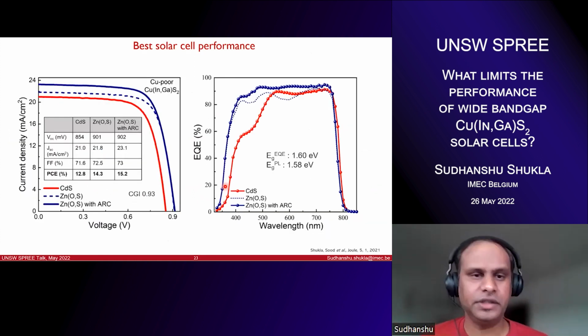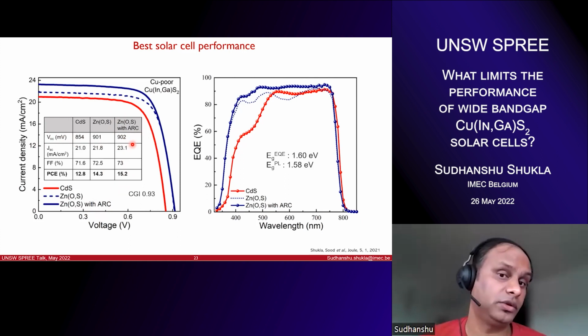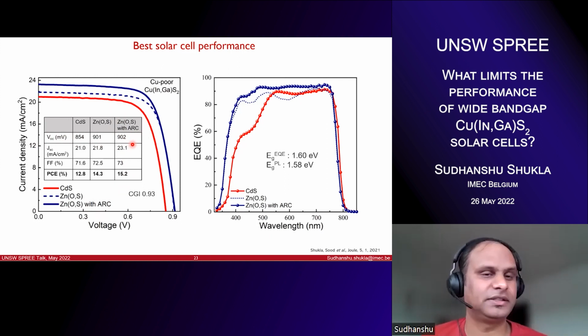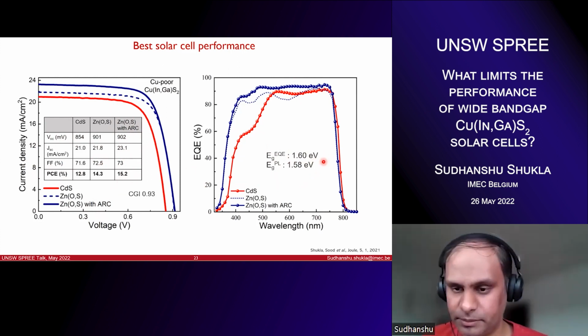So this is our best solar cell performance, which was a CGI of about 0.93. And as you can see, with zinc oxysulfide, putting an anti-reflection coating on top of it, we get numbers of about 15.2%. And the good thing is we were very happy about the VOC, 900 millivolts. As of now, as I said, we have absorbers with 1 volt quasi-Fermi level splitting, very high voltages. But the thing is, when you increase the voltages, your fill factor and so on sometimes becomes problematic, and then you have to do a lot of optimizations. This is the EQE. Of course, the band gap from here is 1.6 eV from EQE. So we have 15% from a 1.6 eV absorber.